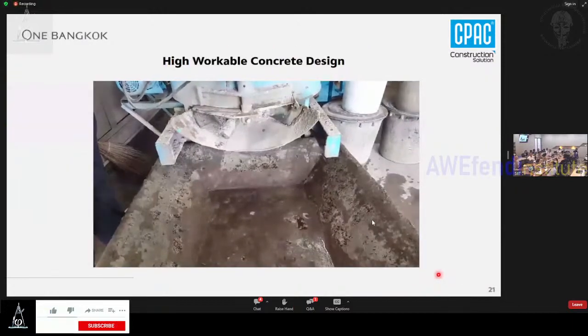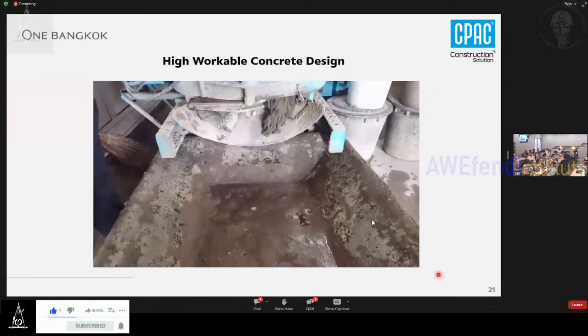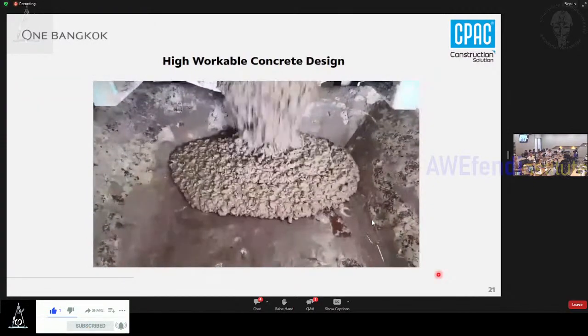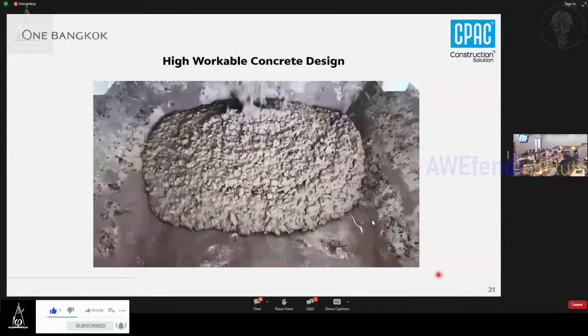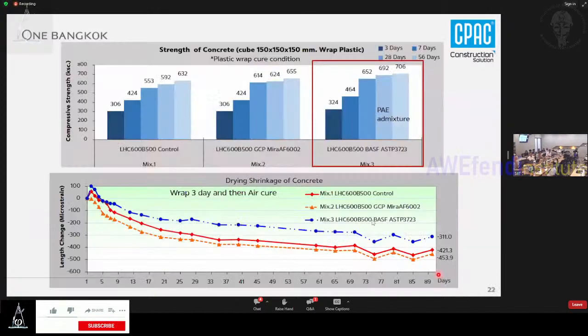And this is our lab test. You can have a look at this. We get the strength around 56 to 70 MPa. This one is in cube, but we can convert it to around 65 something. This is our lab, and we tried to check the shrinkage as well. And we select the proper admixture to be used for the project.